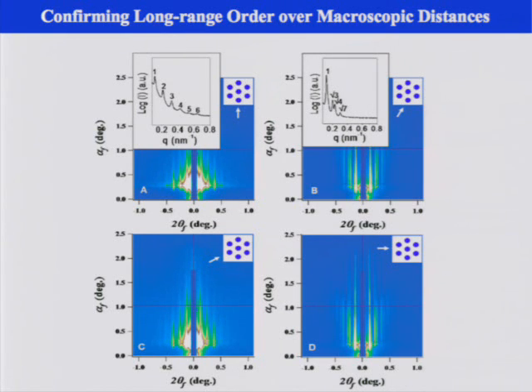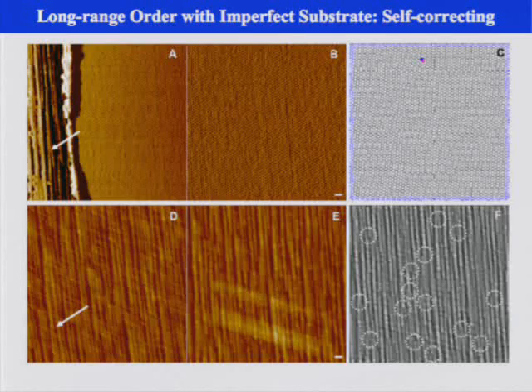Otherwise you are going to see a mixture of hexagonal grains starting to rotate. You're going to see 1 over square root 3 over 2, and you wouldn't see this clean diffraction pattern of the sample.